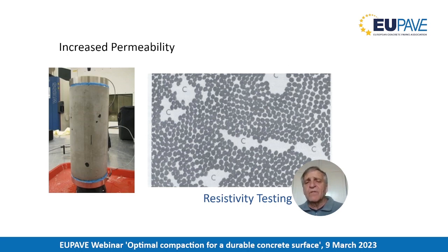Another piece of non-destructive testing is resistivity testing. It's not destructive. We're looking at pore development, and that pore development comes from, if you look at some higher frequencies and you move some water up to the top on finishing, it has a tendency to leave a little bit of a capillary system near the surface, or these pores, and we kind of want to stay away from that, especially in the northern section of where I come from, where they use a lot of chlorides to de-ice.